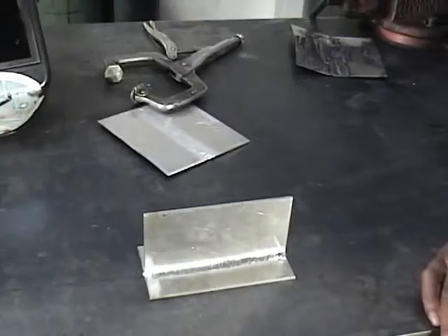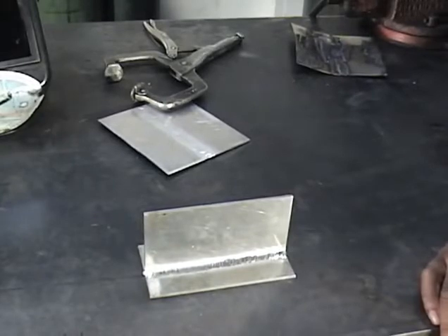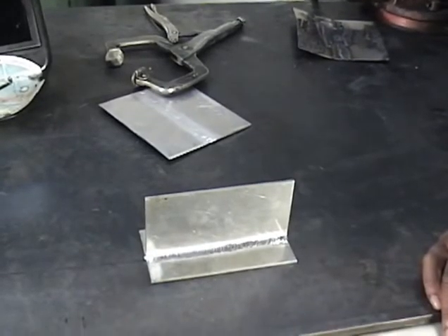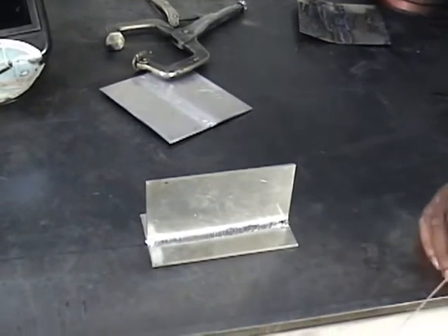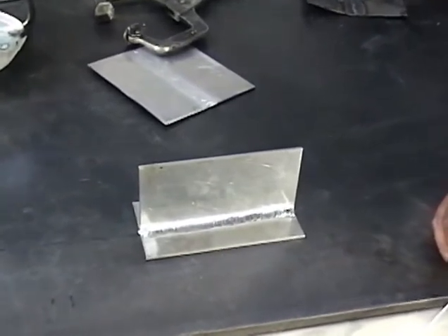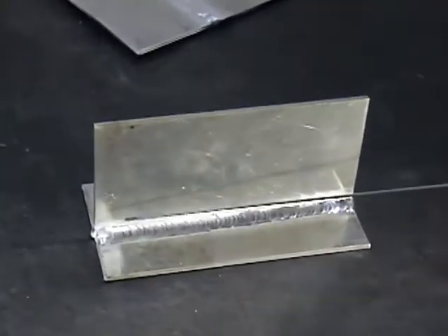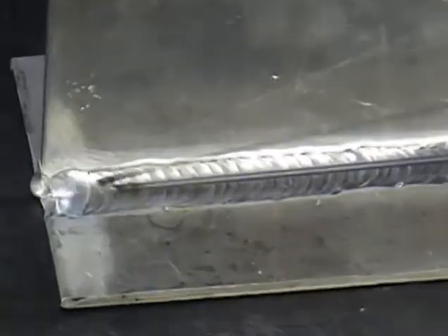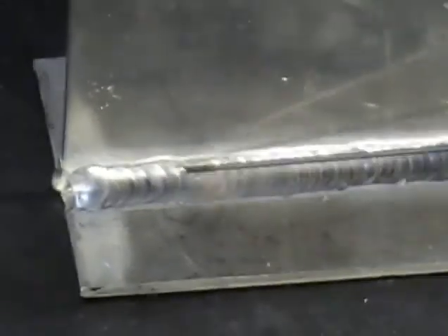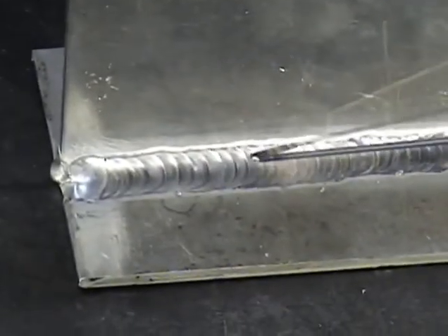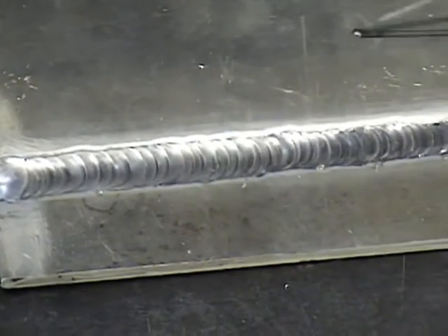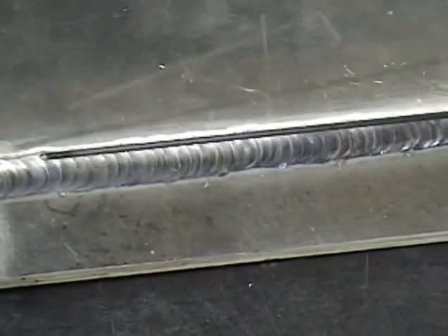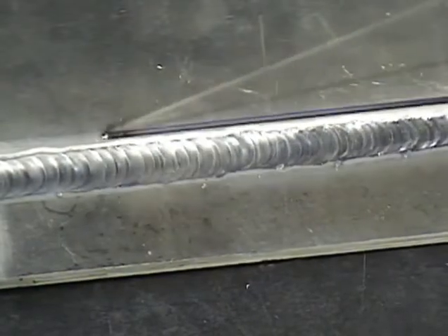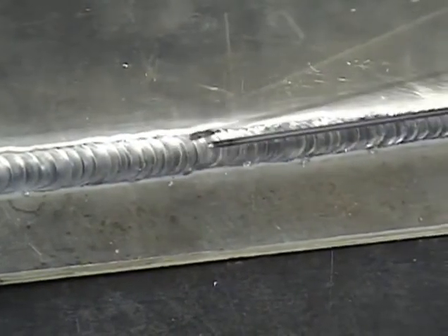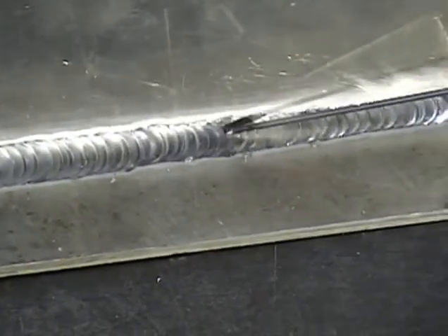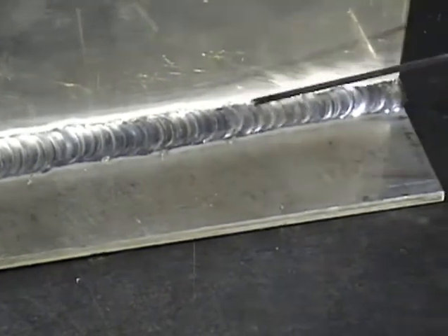Okay, we just finished welding our 6061 T6 aluminum in a T-joint formation. And you can see here, this was welded AC, not DC. What we're looking for is each bead to be interlocked behind the other one with no visible porosity in the weld and the top of the weld. You know that's a clean weld. You can look at the toe of the weld and see that there's no undercut. The edges look nice. Each bead is locked behind the other bead. That is what you're looking for.